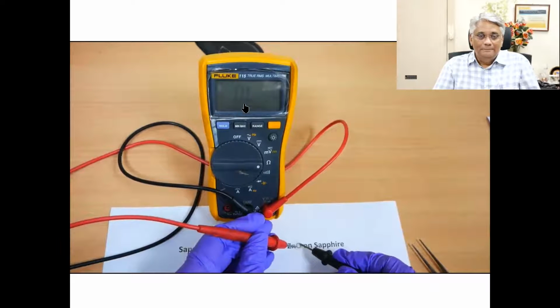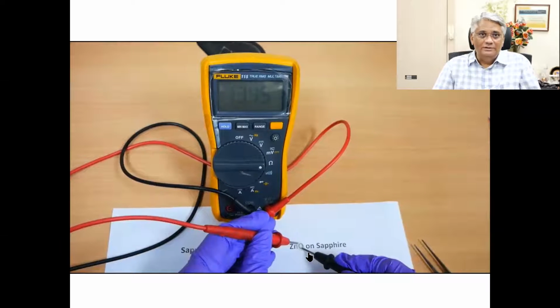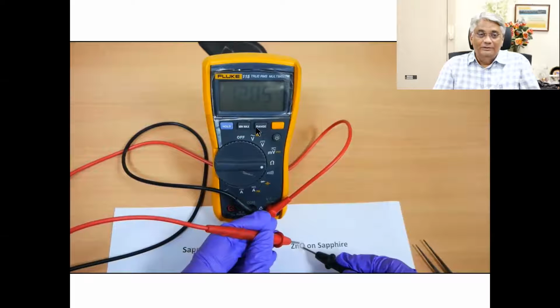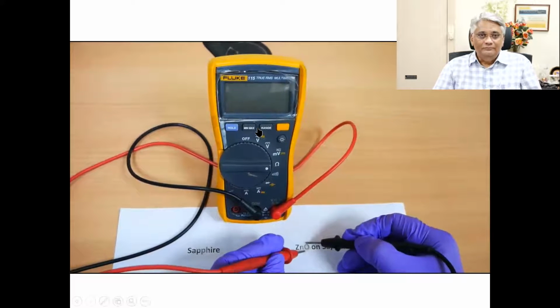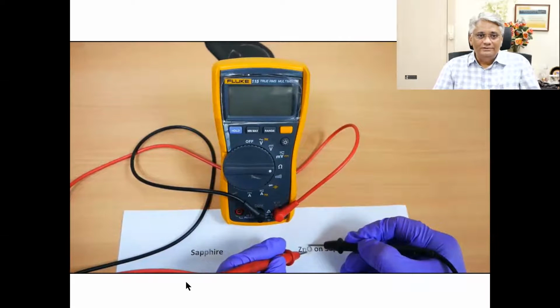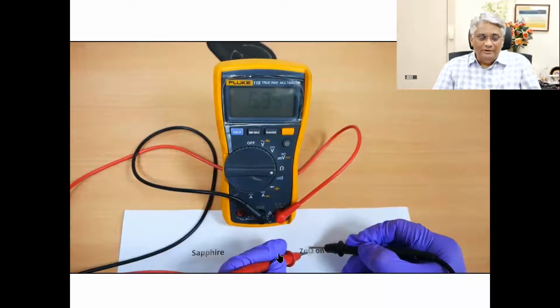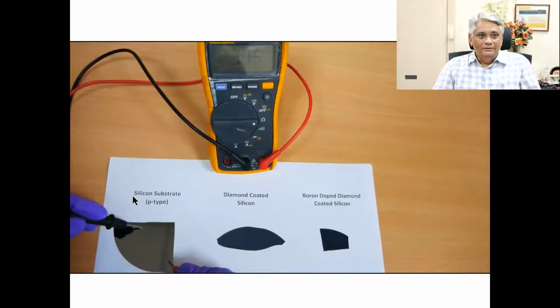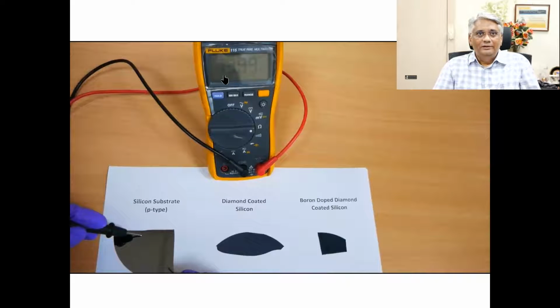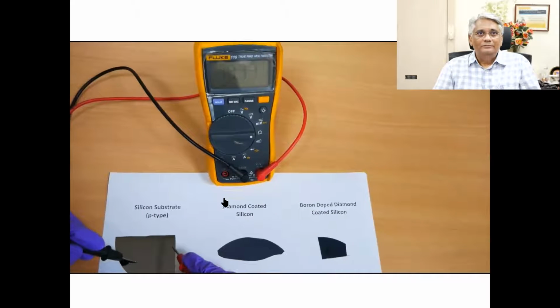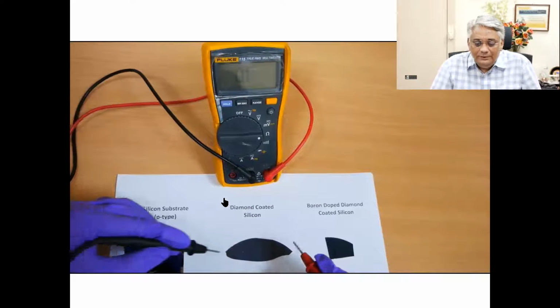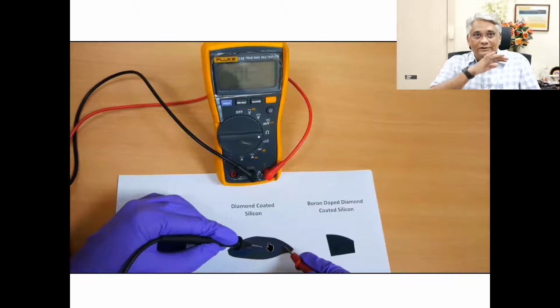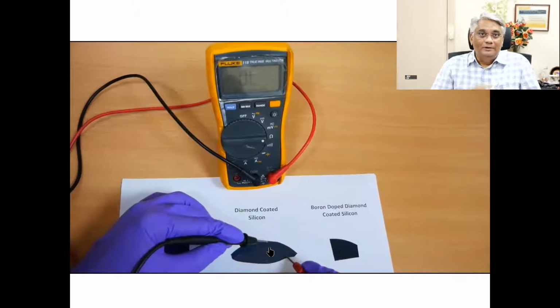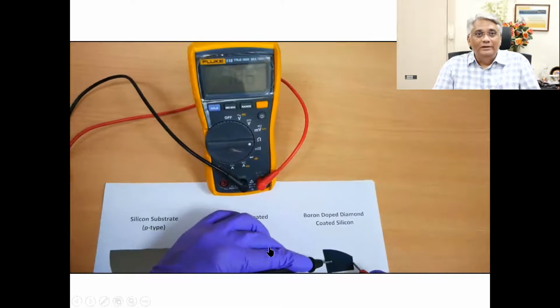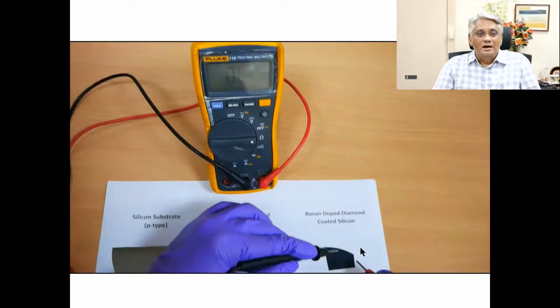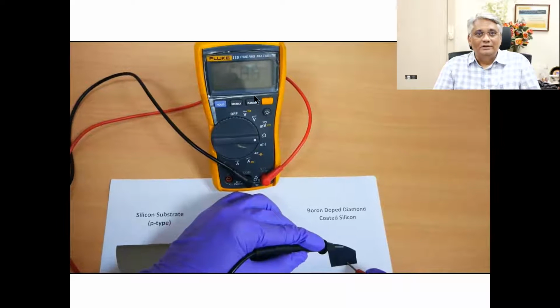So right, see that. Now if I dope zinc oxide with aluminum, the resistivity further comes down. The conductivity increases. That's second case, bare sapphire, and zinc oxide on sapphire. Then silicon P-type substrate, typically a few mega ohms of resistance. Yeah. Now diamond on silicon, a thin layer of diamond on silicon. Diamond is insulating, but diamond and silicon is required for heat spreading applications. And this is boron-doped diamond, which starts conducting, right?